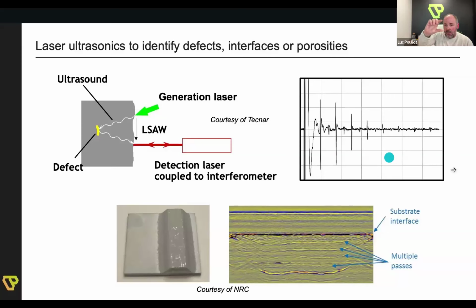Those echoes obviously decrease in intensity over time, pretty much as a Bessel function. And they are created by the wave that hits the yellow defect and then comes back. So basically, the time span between two of those peaks corresponds to the wave traveling twice the distance from the surface to whatever defect we're interested in. That's a very long story made short, but let's get practical and look at the bottom picture. This is a cold spray buildup.